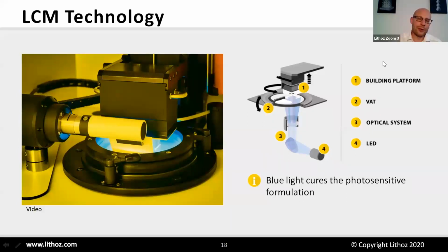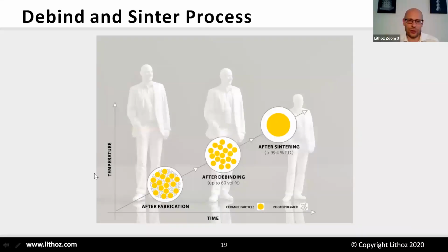So after we have printed, we have, as I said, the so-called composite. So we have here the ceramic particles and the binder, which holds the particles together. Then we simply burn off the binder and we are left with the ceramic particles. And then we have to compact them. This compaction, so pulling these particles together, is called sintering. And by having this sintering, there is a shrinkage of the material or of the part.